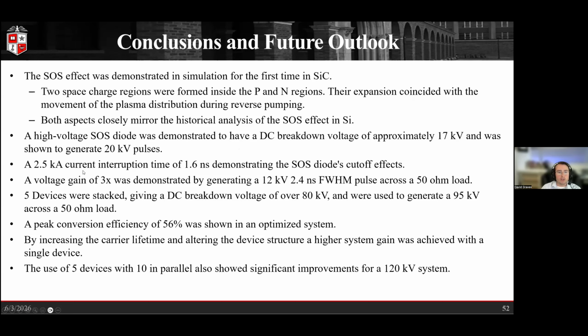With that, a 2.5 kiloamp current interruption time of 1.6 nanoseconds, which demonstrates the very fast cutoff effect from our SOS diode. We're able to get a voltage gain of about 3x on these devices, with our pulse width being 2.4 nanoseconds across our 50 ohm load. Again, when we put 5 devices in series, we get a DC breakdown voltage over 80 kV, and we can use that to generate a 95 kV pulse across a 50 ohm load.